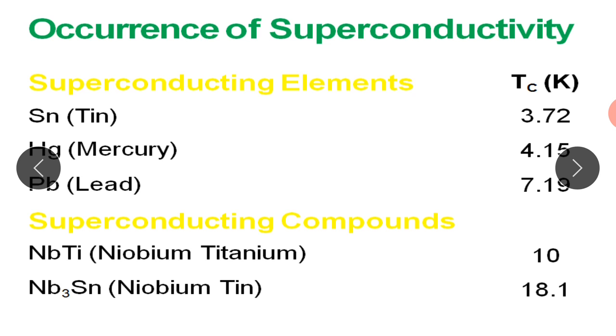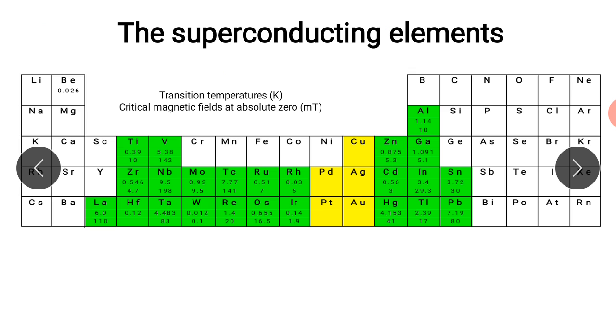Here is the occurrence of superconducting elements. Tin is 3.72, mercury is 4.15, and lead is 7.19 degrees Kelvin. Superconducting compounds are niobium titanium, and niobium tin, which is 18.1. This is the superconducting elements. These are the transition temperatures in degrees Kelvin and the critical magnetic fields at absolute 0.